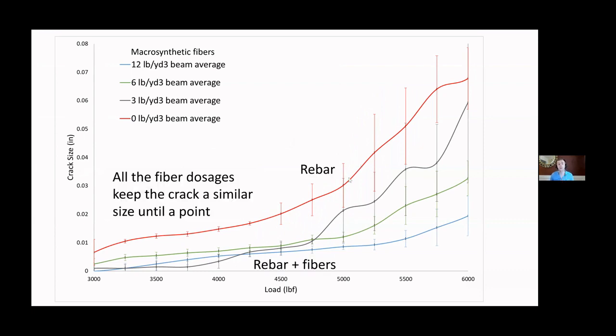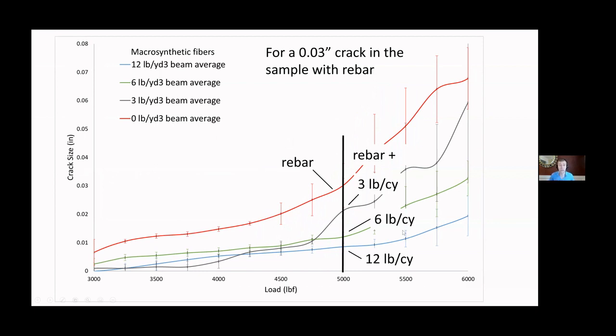Well, actually, I'm going to show it. Here's the rebar at the top, and here's the rebar plus the fibers at the bottom. And again, look at these. The fibers are all doing a good job. They're all keeping the cracks small, and then all of a sudden we start to see a little bit of difference in performance here. But at a crack size of about 0.03 inches, and that's one in the literature people talk about, that's an ACI recommended crack limit for certain size structures.